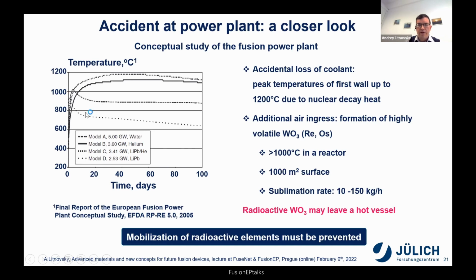As we see, there will be a huge neutron environment, and these neutrons will activate the material, which will produce nuclear decay heat. So in the absence of coolant, the vessel components will be heated just by this decay heat. And the temperature will exceed 1000 degrees C for the tungsten cladding. Then imagine the earthquake destroys the vacuum vessel, and air enters it. With all these conditions, with this radiative cooling, this high temperature can last for several months. In contact with the air, tungsten, such a heavy material, oxidizes and creates a volatile oxide. So tungsten oxide is volatile, it is an aerosol.